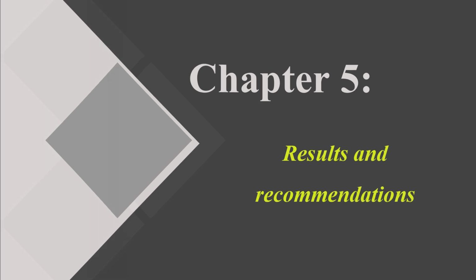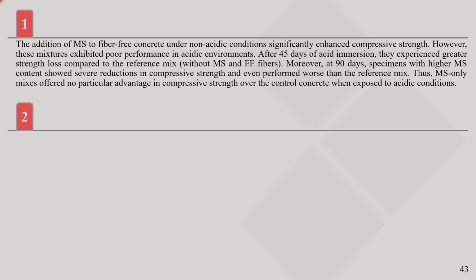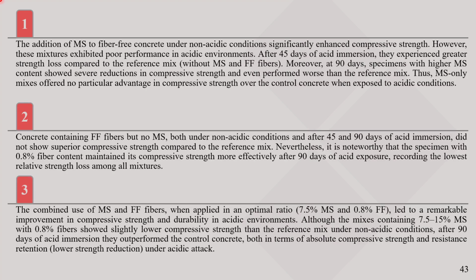Finally, we reach the last chapter, results and recommendations. In this section, to summarize the findings briefly, the presence of microsilica alone under acidic conditions does not have a positive effect on compressive strength and can even lead to further reduction. On the other hand, when only fibers are present, the compressive strength remains relatively stable, showing the least relative reduction among all mixtures. However, when both additives are used simultaneously, samples with the highest fiber content along with a certain amount of microsilica, up to 15%, exhibited excellent performance in terms of both compressive strength and strength stability after 90 days in an acidic environment, compared to the reference sample.